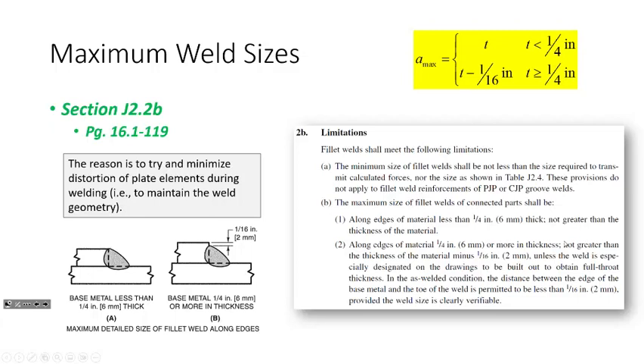For most connections. If you've got a really thin plate, like a 1/4 inch or thinner, so we're talking about really thin plates, we say, what the heck, just fill the whole thing up. But for most structural connections, we've got to back that off a little bit so that we maintain the geometry of the plate. So for minimum weld sizes, we're trying to avoid the heat sink effect. For maximum weld sizes, we're trying to avoid distorting the plate by melting that corner up there. That make sense? All right, any questions so far?